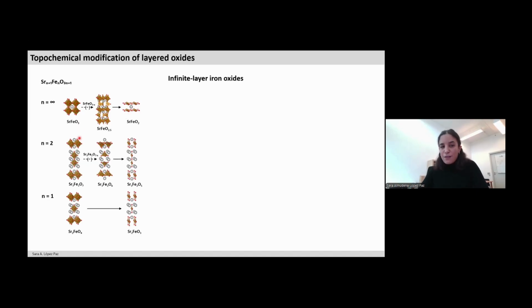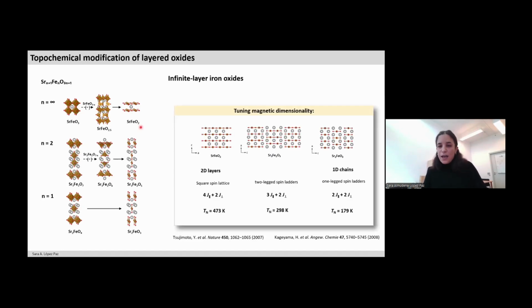So the potential of this method was indeed demonstrated. You could select different precursors, and in this way really anticipate which product you would get. And in this way, you could, for example, access different dimensionalities in these compounds, from infinite 2D layers down to spin chains with intermediate ladder configurations. But I realized that here we were all the time cutting the dimensionality in the perpendicular direction, we could say, but there was no example of how we could split these layers in this direction. So for this, I thought, okay, let's increase a bit more the complexity of our initial phase.